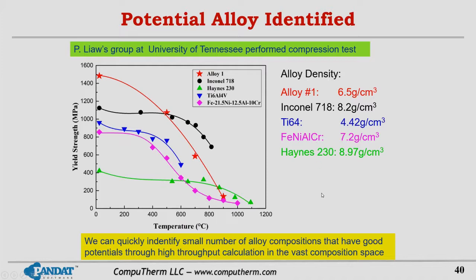This example really demonstrates the alloy design idea: we can use high throughput calculation to screen a wider composition space, and then down select a few potential alloy compositions for experiments. This significantly accelerates the design process.